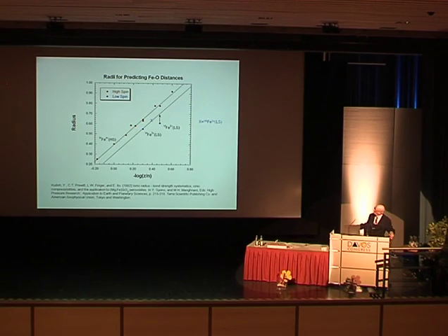And it turns out that using pyrite, which gave us this number, was not a good thing to do, because the disulfide aspect of pyrite makes the Fe-S distance shorter than it would be in a single low spin situation. So if you have a table of radii from Shannon and Prewitt, or from Shannon, go to your ferrous iron in low spin octahedral coordination and move it up to this point here.